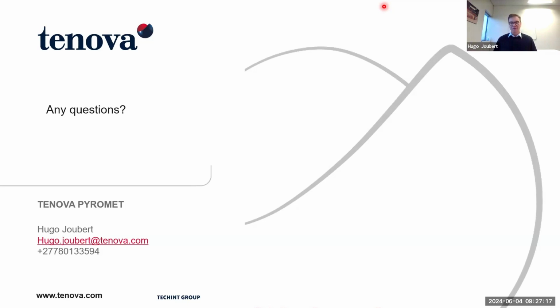thing that you need to think carefully about is the effect on that lower sidewall area. Because we don't like to put copper cooling in that lower sidewall, as I discussed. So you need to design it very carefully to make sure that the wear rate is not going to be too high. That's quite important because we know that in most processes, slag is the most aggressive to these bricks. But with these PGM furnaces and this very high superheat, the matte itself is also extremely aggressive to these bricks. But that design with the graphite works very well.